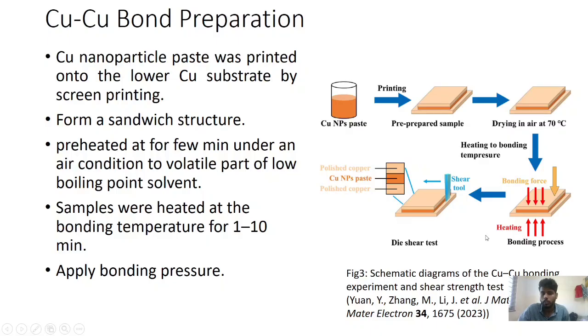After making the copper paste, this is the actual procedure of making copper bonding, which is seen in the pictures. First we take the copper paste and print it onto the copper substrate using the screen printing method, and put one more copper plate on it in the form of a sandwich structure. After that, we preheat it at some temperature. Then we pressurize it from both sides and heat it at bonding temperature. The heating time is approximately 1 to 10 minutes. After that, the bonding takes place. So as we see in the figure, it is the actual procedure of making copper bonding.